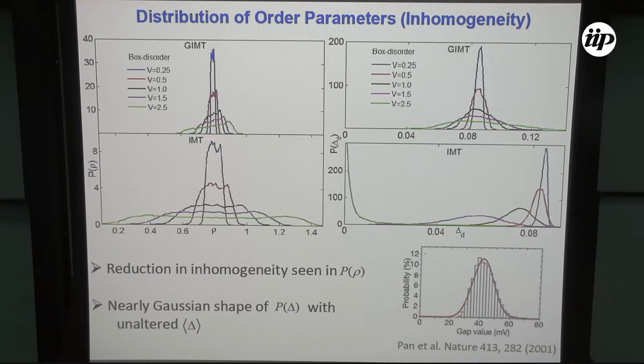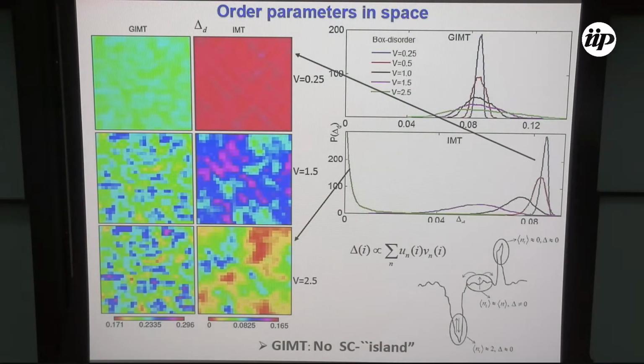As a result, if you look at the gap distribution in GIMT, for homogeneous it should be a delta function. But once you increase disorder, it widens, it becomes a Gaussian. More or less for high disorder, it still remains Gaussian. The width increases, but the mean value remains at the same place. This was very similar to what was seen in experiments, a Gaussian nature in the distribution of the gap value. Now, in order to understand what happens locally, let me show you the right-hand panel first.